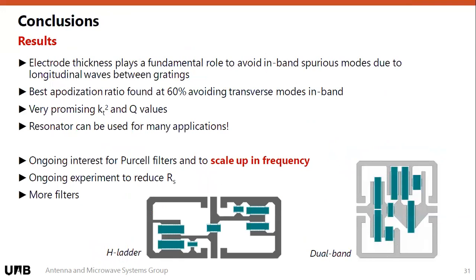Okay, this is the point at which we stopped initially. So now I'm writing the PhD, and I'm working for this company. But what we saw is that we found out how to play with the thickness of the electrode, so as to avoid spurious modes above FP, we found the best apodization ratio to avoid the transverse modes, and then we saw that we were increasing in coupling and in Q. We have very promising values now, so that we have a resonator that we know we can trust, and we can actually start building more complicated structures